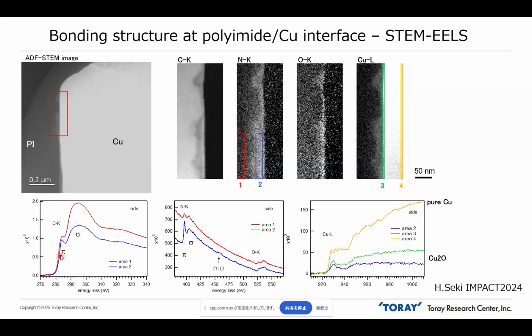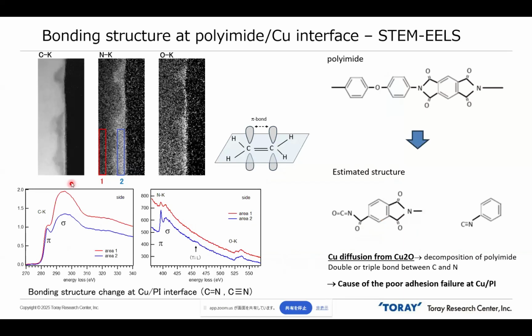Here we can see two kinds of peak, pi and sigma. In area 1, the inner part of polyimide, the sigma peak intensity is much higher than the pi peak intensity. But in area 2, around the interface, the peak intensities of pi and sigma are almost the same. The tendency is almost similar in the nitrogen K-edge. In area 2, close to the interface, the pi peak intensity is higher than in area 1. This kind of high intensity of the pi peak means there is a double bond or triple bond between carbon and nitrogen atoms. So by using these experimental results, we speculated the chemical structure of the interfacial layer.